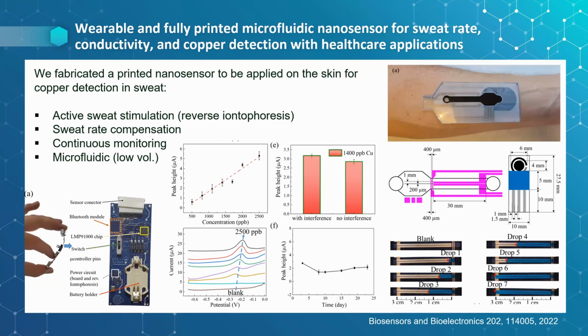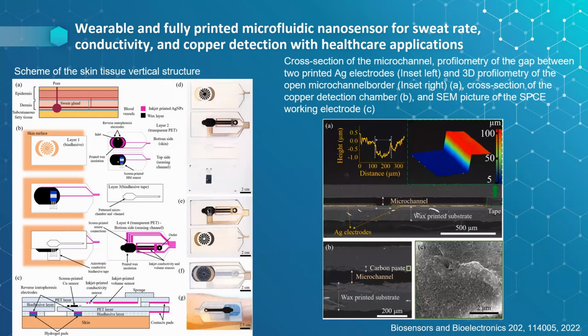Here is another example of the wearables we are developing. This is a wearable with microfluidics for sweat rate measurement, but also copper detection, which is of interest for several healthcare applications. So all of the electronics is integrated and wireless, in which this sensor is able, thanks to the simple microfluidics, to measure this sweat, and using electrochemical stripping, it is able to detect the copper in the sweat. Here are some details of the device, and also the thickness, the electrodes, the channels that are incorporated in this device, and more details about the adhesive layers used and where the electrodes are connected for this measurement.